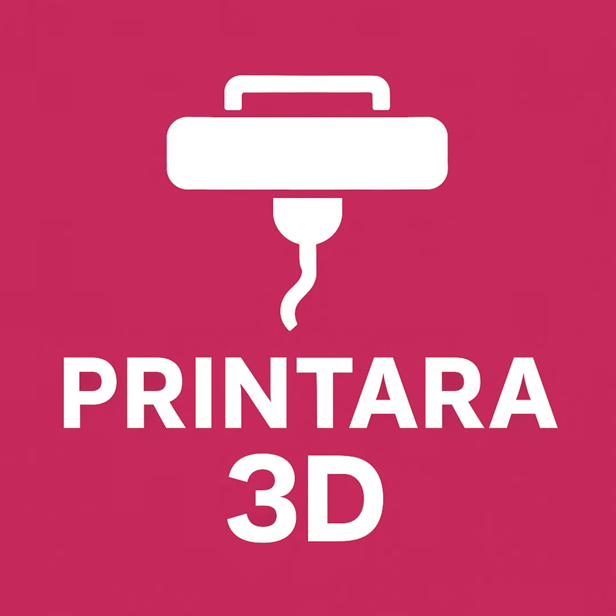You are guessing correctly again. You absolutely pay for that extreme performance in terms of printing difficulty. Polycarbonate is notoriously challenging to print. It needs extremely high temperatures, even higher than ABS, for both the nozzle and the bed. And like ABS, a heated print chamber isn't just recommended. It's pretty much essential to prevent warping, cracking, and ensure the layers fuse together properly.